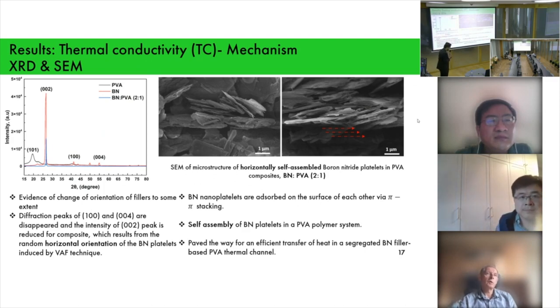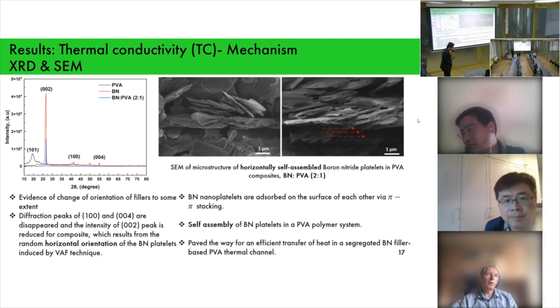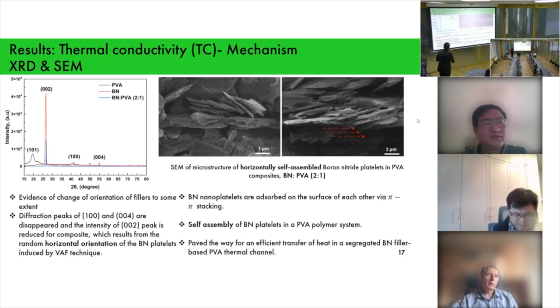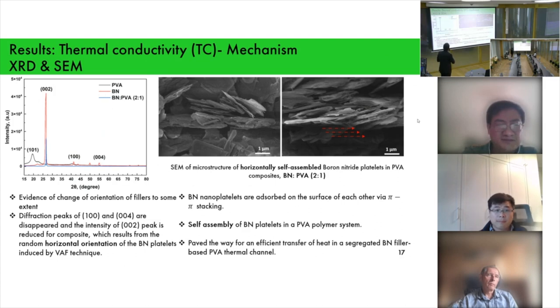Actually, it's not clear for me, but you have the polymer matrix and you should prepare a diffractogram for any angles. And this peak, I say about peak 101, does not disappear in the mixture of polymers with boron nitride. It's maybe weaker, maybe at higher levels, but it should be present on your diffractogram. Okay, but it shows like. And it's very, very strange. Maybe you have another comment.